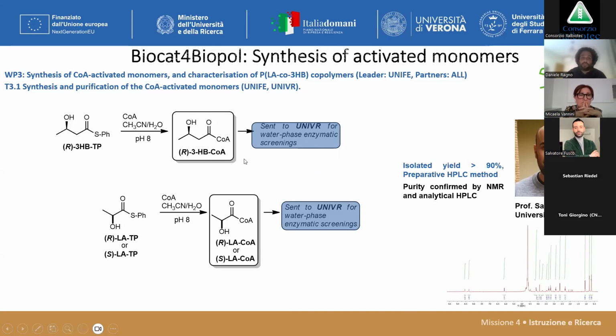The most problematic part of this work was the isolation. It was done in collaboration with Professor Salvatore Pacifico of my university. After a little struggle, we were able to isolate the products with a high purity level, confirmed by NMR and analytical HPLC, and the conversion and yield of this process was very high, more than 90%. So little waste of coenzyme A, which I can tell you is not the cheapest thing in the world.